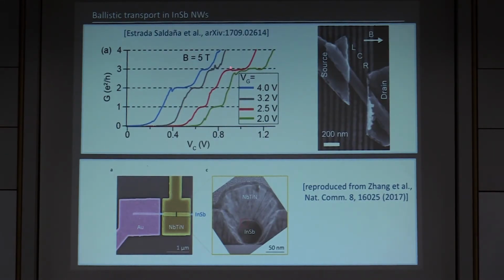So these are our data. I originally planned to discuss this, but there is no time for that. But just to show them, there are some nice plateaus at 5 Tesla in the same material, indium antimonide. And these are the structures that were discussed this morning, where conductance quantization was observed also at zero magnetic field. But I want to stress the fact that in all these structures, the length of the channel is rather short. So here we're talking about a few hundred nanometers, and here as well the channel is rather short.